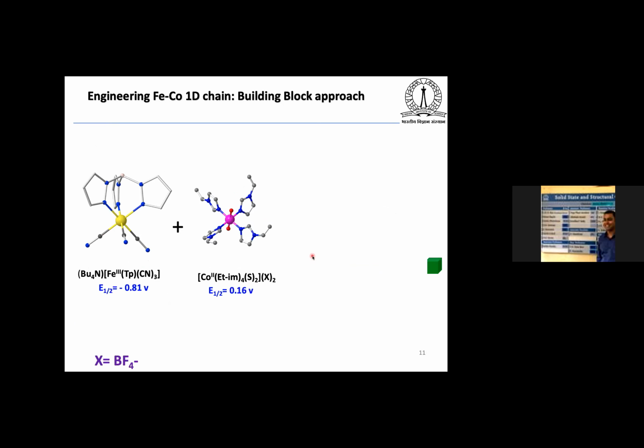And another interesting thing happened. Instead of using vinyl imidazole, when you use ethyl imidazole, we got only one type of crystal, that is needle type of crystal. And you can see the redox potential difference is not that much. It's almost close to 1 volt.